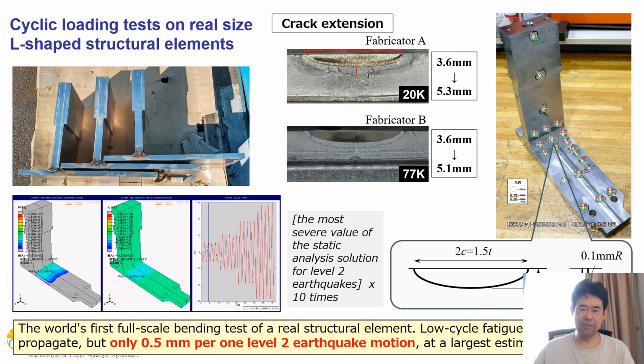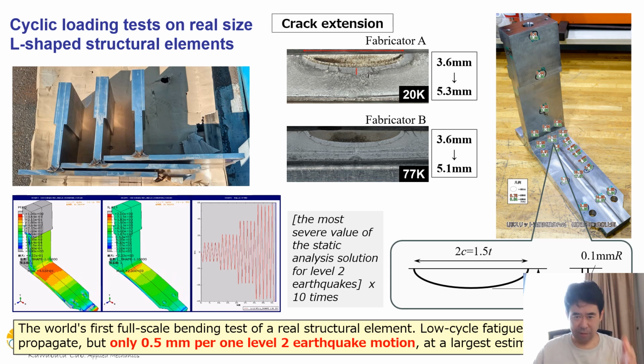So this slide shows several test examples of L-shaped test using cryostat test machine. Applied material, welded joint using standard 316L plate and weld material and fabrication in Japan showed good LCF properties, low cycle fatigue properties regarding anti-unstable fracture initiation, and low cycle fatigue properties. This test will be the best evidence for actual application.